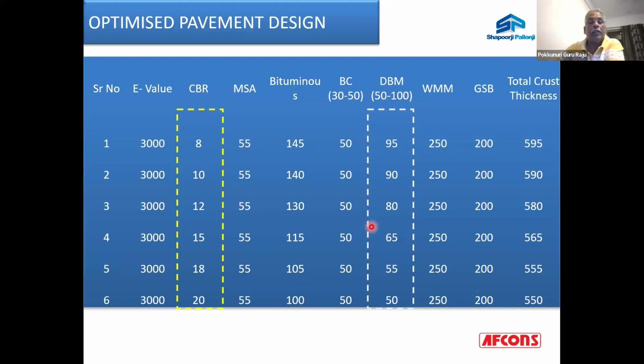The meaning is, if you see subgrade in the natural condition, it's quite possible that in a particular area you get a CBR of 8, somewhere you get a CBR of 10, somewhere you get a CBR of 12. Maximum what you get is 12, not more than that, because I have seen this in my 30 years of experience. I have not encountered a soil which has a CBR of more than 12 to 13. Sometimes it is less than 8 also, like it goes down to 4, 5 also.